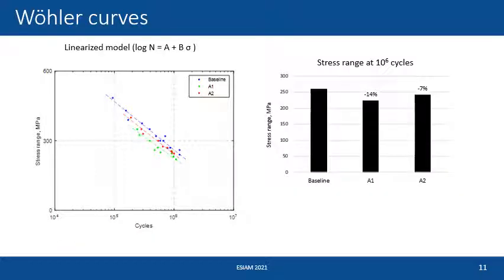To summarize, if we consider only the reduction in the stress range at 1 million cycles, we saw that compared to the baseline, in the A1 process parameter set we have a reduction of 14%, while in the A2 process parameter set we have a reduction of only 7%.